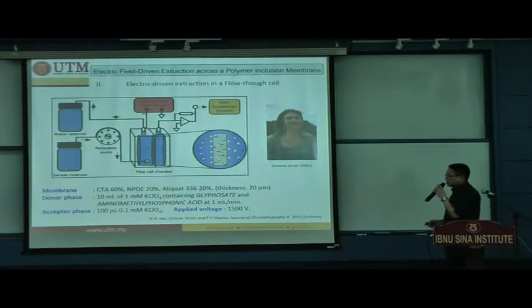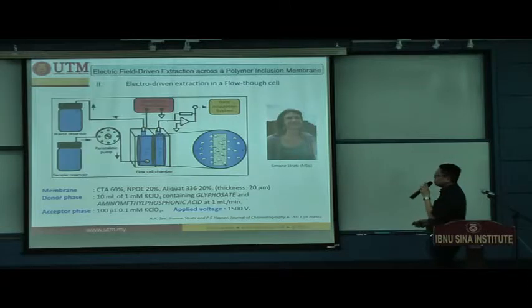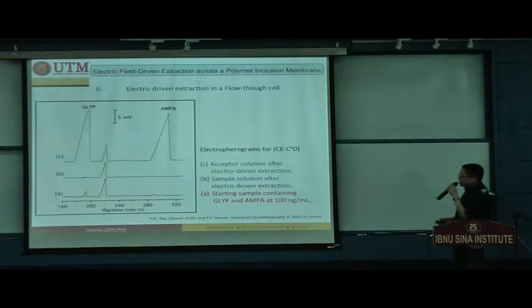And the acceptor phase is in a stagnant position, which is only 100 microliter, and the applied voltage that she uses is 1500 volts. So this is a very important electropherogram showing the first one is the starting sample containing glyphosate and AMPA at 100 nanogram per milliliter. This is without any extraction, there's no treatment at all. And after the extractions, we actually collect the sample after extractions.